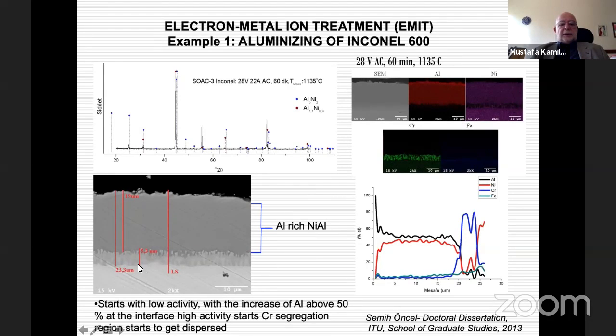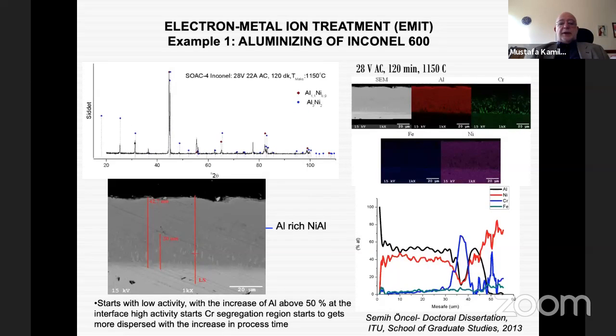Here you see the thickness of the total layer is about 23 microns. Because it starts with a low activity at the interface, and afterwards it starts to become high activity, we see that chromium segregation starts to get dispersed by changing the mode of diffusion. When we further increase the temperature, we also end up with an aluminum-rich nickel aluminide formation on the surface. And again, this process started with a low activity process. And then, as you see, these chromium particles that are segregated at the interface start to get dispersed in the structure, and we can increase the coating deposition thickness to 42 microns.